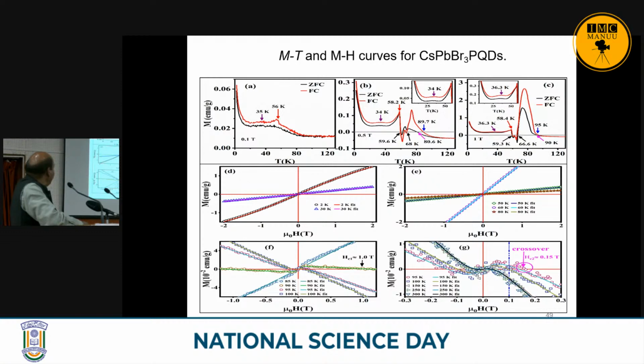This is the zero field cool and field cool. You will get some peak coming here. It should not come, but you can see that if you increase the field, the peak also emerges more and more. Or this is the MH curve. This is showing diamagnetic property at room temperature, but if you go to lower temperature, it is showing some ferromagnetic properties. So this is showing some transitions here.